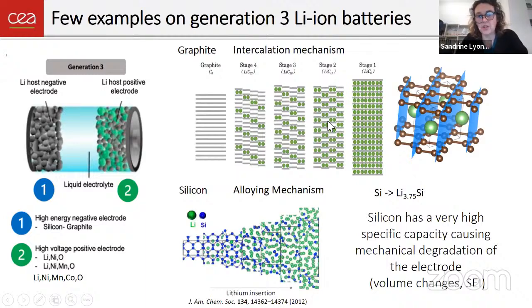And recently, another material, silicon, has attracted a lot of attention because silicon is able to store something like 10 times more lithium ions than graphite. And this is because it's a completely different mechanism. It's an alloying mechanism where basically we can reach phases where we have almost 4 lithiums per silicon. This is very nice, but due to that, there's a number of degradation problems in silicon anodes, mechanical degradation, and practically silicon is not usable as a pure anode for a battery. And therefore, the trend actually is to blend silicon with graphite and try to keep the best of each of the materials by making these high energy density composites.